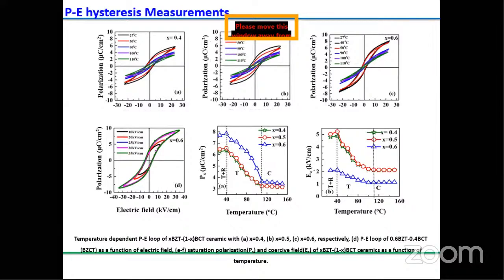So our ferroelectric polarization measurements, the P-E hysteresis loops, also support that these materials have two phase transitions. One is rhombohedral, which transforms to tetragonal, and tetragonal transforms to cubic. Similarly, EC also exhibits the same behavior. If you observe these polarization values, we can say that x is equal to 0.6 has the better polarization.